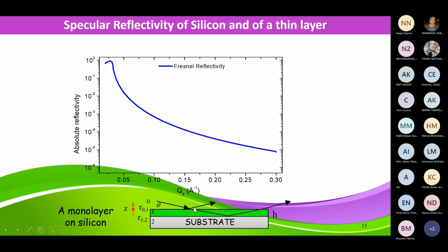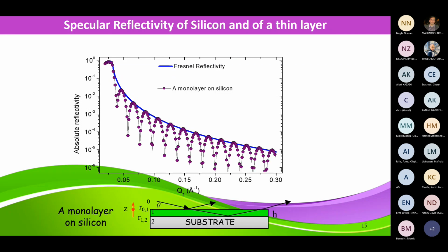This ray is reflected here, but part of the ray is going to be transmitted in the film, reflected at the interface with the substrate, and the two rays which are going to go out, they are going to interfere. So what's going to happen is that instead of seeing a reflectivity like a smooth decay, you will see some fringes. And the fringes are related to the thickness of the film. Typically, those are known as the Kiessig fringes, and the separation between two fringes is just related to the inverse of the thickness. So if you measure the distance between two fringes, you have direct evidence of the thickness of the film.